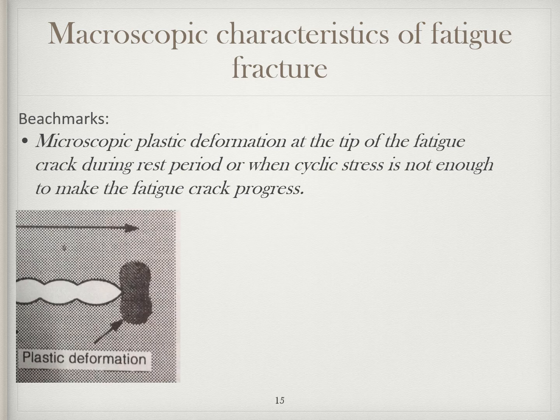The figure shows the crack progressing from left to right, and there is a highly strained zone at the tip of the advancing fatigue crack. So let's see over here. The crack is progressing from left to right, and this is the tip of the crack. Here there is a highly strained zone because of the plastic deformation that is present over here.